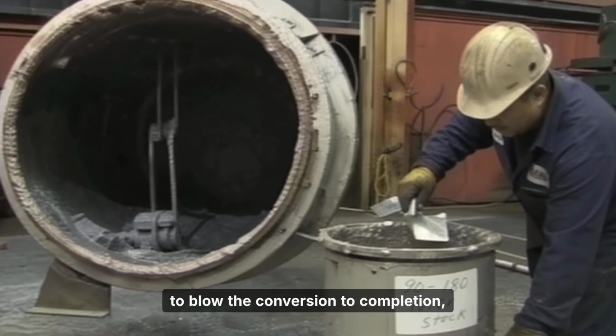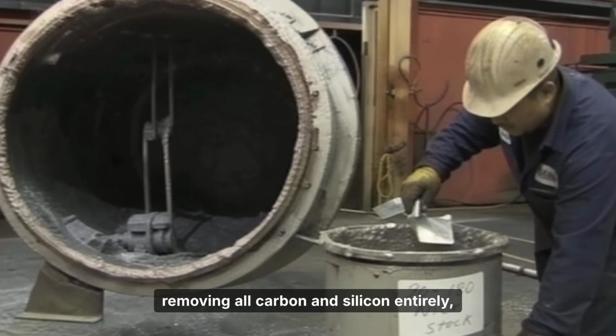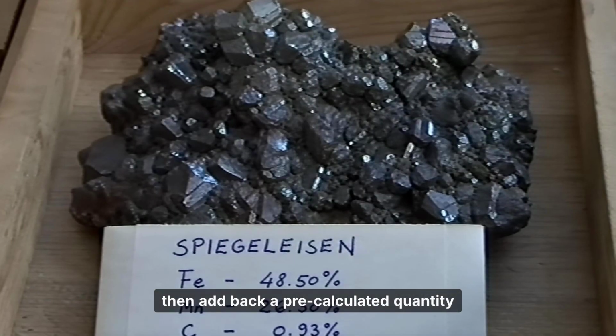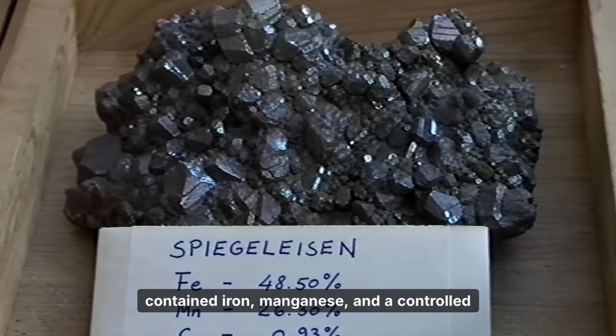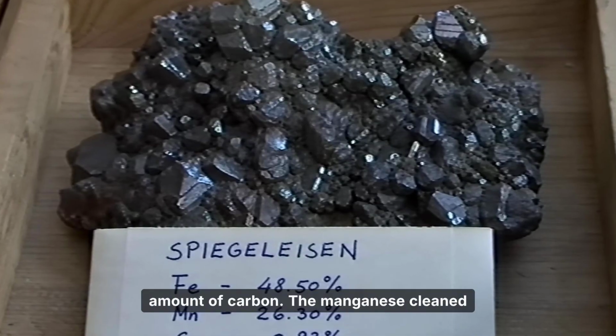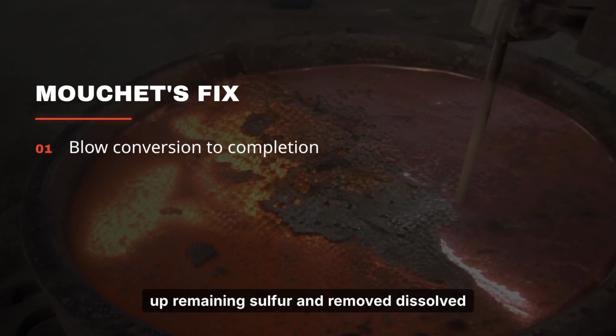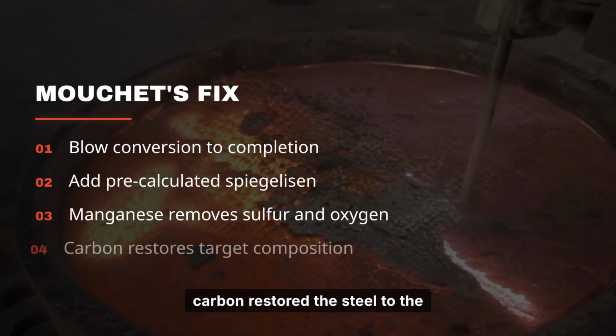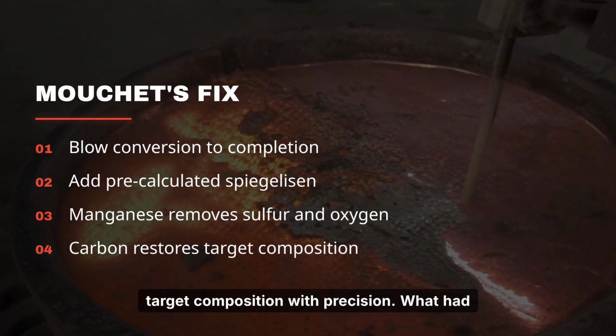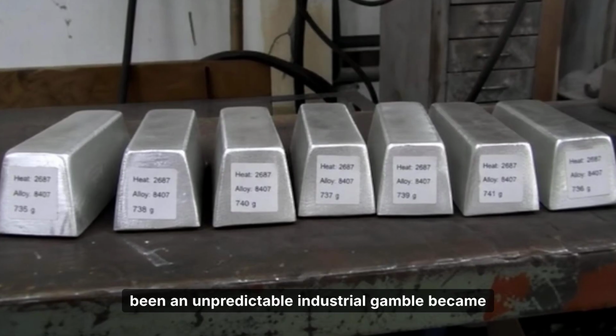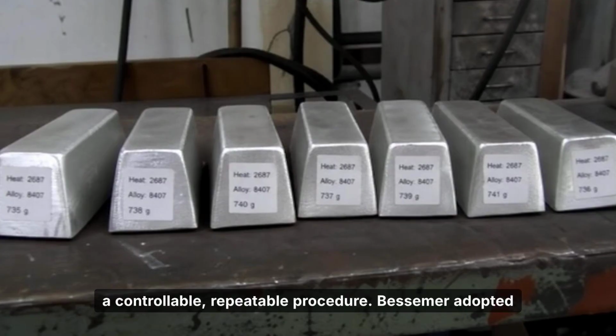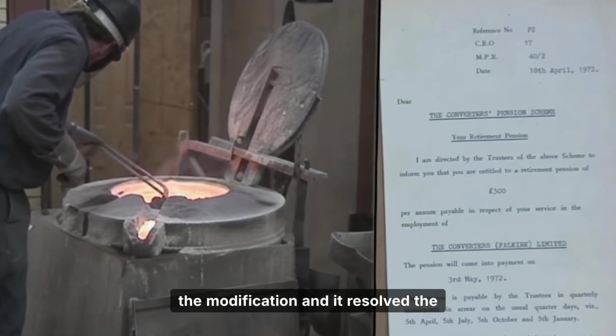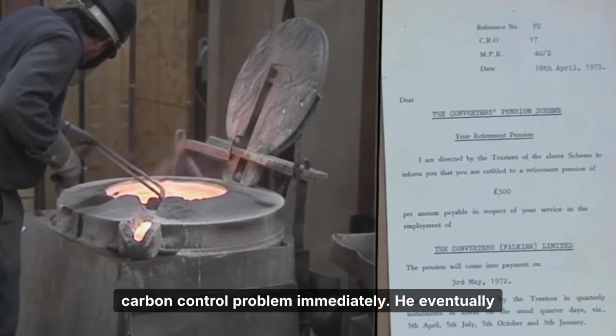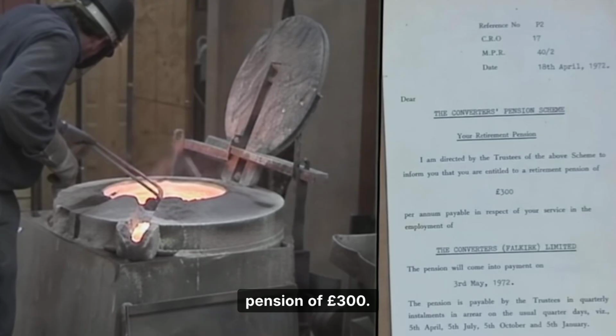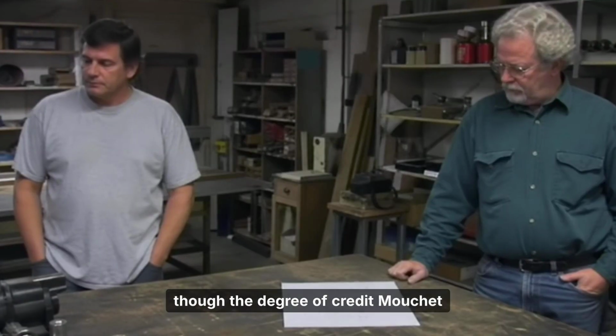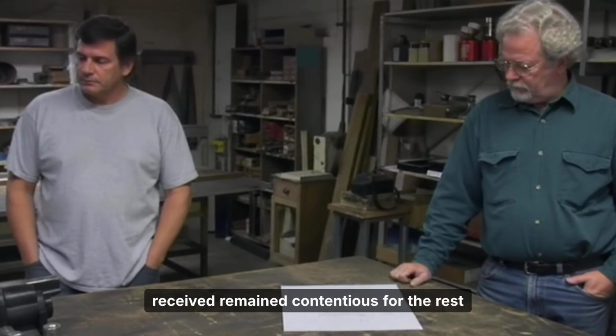His solution was to blow the conversion to completion, removing all carbon and silicon entirely. Then add back a pre-calculated quantity of an alloy called Spiegeleisen, which contained iron, manganese, and a controlled amount of carbon. The manganese cleaned up remaining sulfur and removed dissolved oxygen from the melt, while the carbon restored the steel to the target composition with precision. What had been an unpredictable industrial gamble became a controllable, repeatable procedure. Bessemer adopted the modification, and it resolved the carbon control problem immediately. He eventually agreed to pay Mushet an annual pension of £300, though the degree of credit Mushet received remained contentious for the rest of both men's lives.